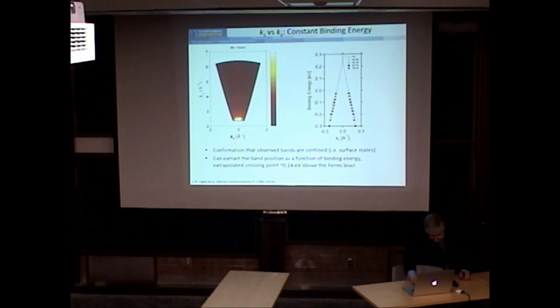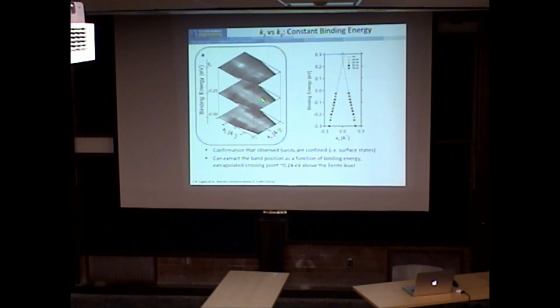So if I do this, we're going to try this little calculation here and see if this thing works. And here's the data. You might be able to see that those vertical lines are separating further and further. You see them moving out? Okay, so this has been plotted here on this plot. This is just a snapshot taking different binding energies. If you do this binding energy plot here, we get a Dirac cone. The point is about 240 millielectron volts above our Fermi level, just extrapolating. So at least it looks like we've got a Dirac cone.